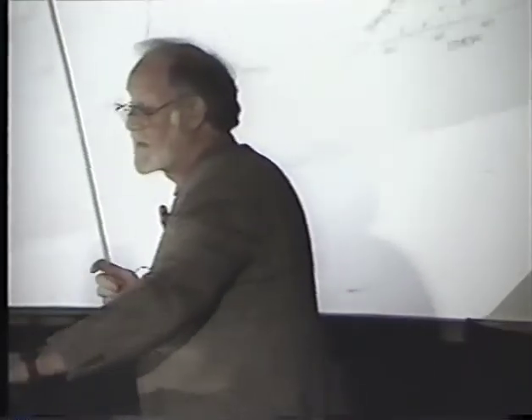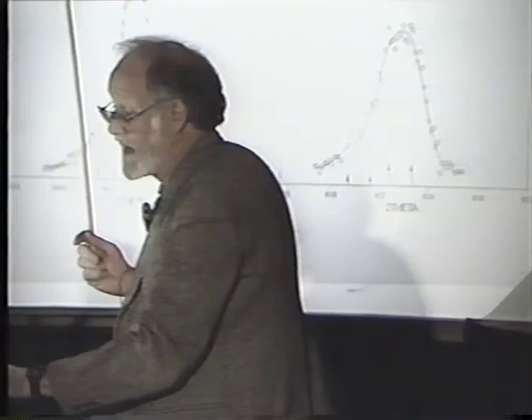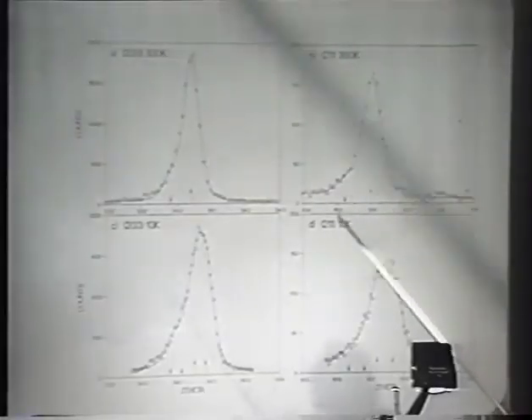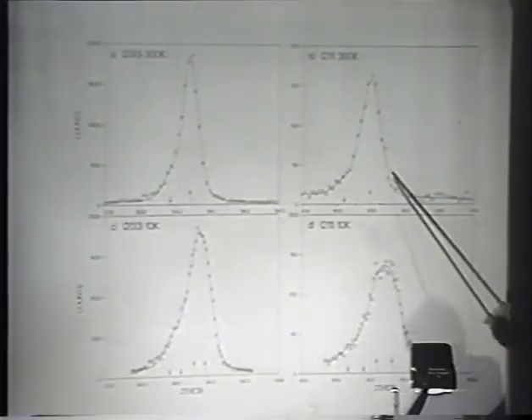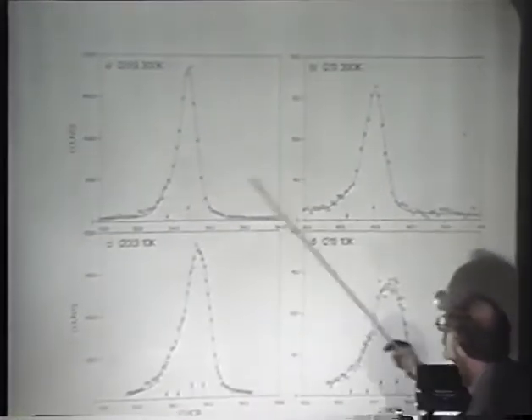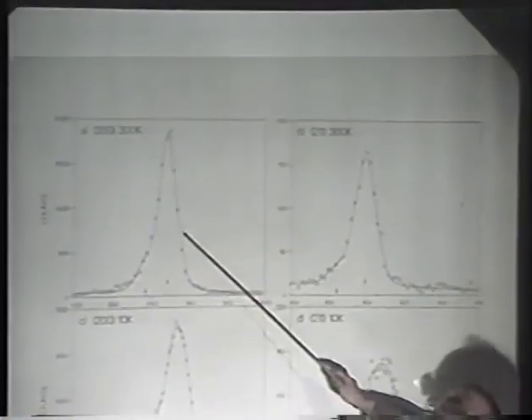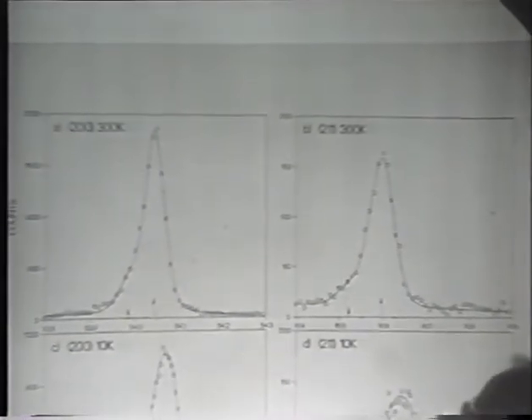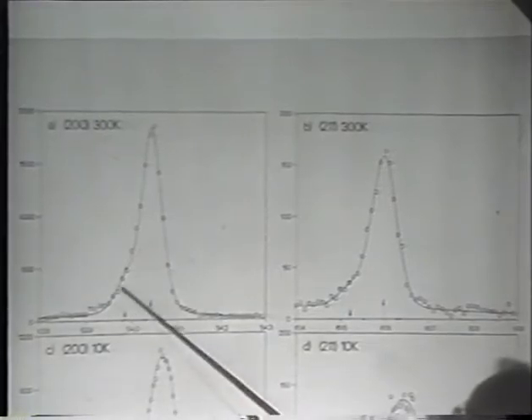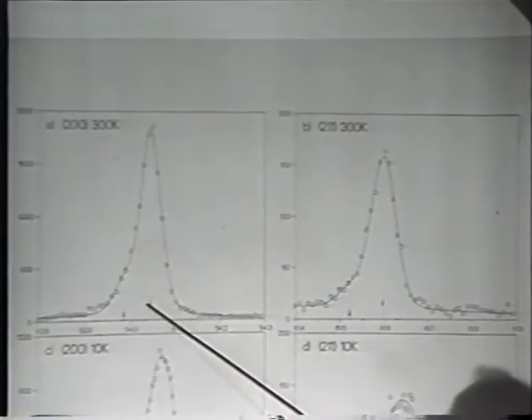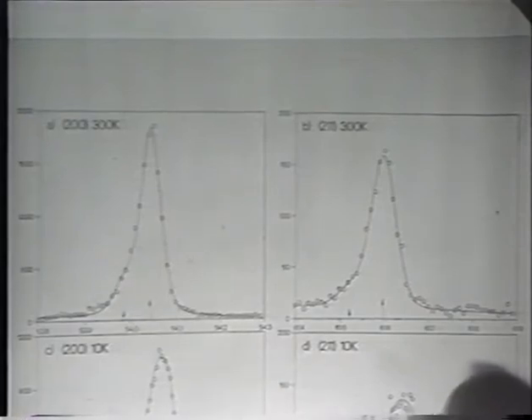And when you have such resolution and intensity, then you can start to see the sorts of things we're talking about. For instance, here's a pair of reflections, the 200 and 211. And just consider the room temperature set for the moment. You see there's a single peak and then a shoulder on that peak. This has been least square fit now to 2 peaks, one of them centered here and one of them centered there, a major phase and a minor phase.